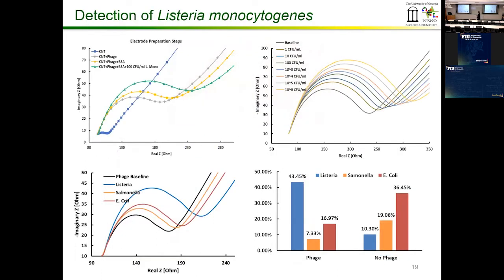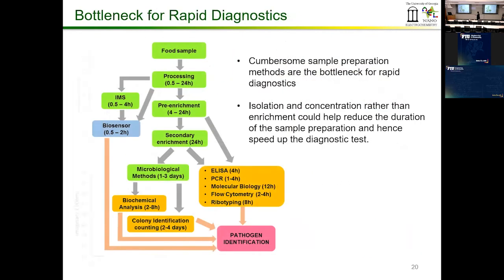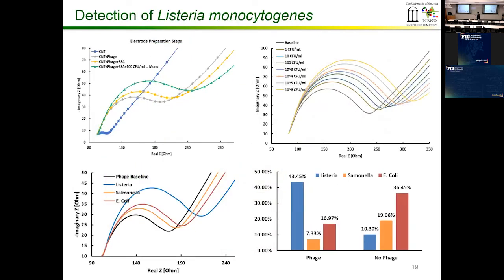There is the third pathogen. I don't have a lot of results because these are published. A similar set of results, you can see that when you have the phage and we actually put another blocker called BSA to reduce the number of exposed sites on the electrode. I don't want to get into that in too much detail, but what has been demonstrated here is very similar to the previous cases where you have the impedance change with the concentration.